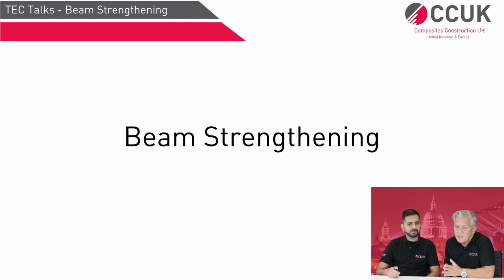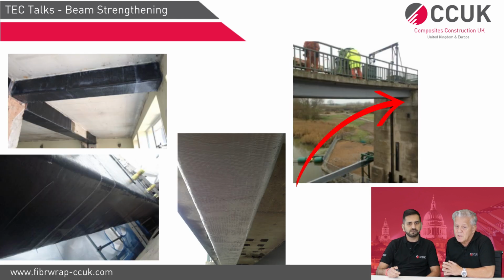So if we're looking now specifically at the beam strengthening side, when you're looking at beam strengthening, what are the key areas? Yeah, so beam strengthening is one of the most common types of strengthening which is done using carbon fibre. Generally beam strengthening is done as it's a flexural element. So mainly the reason for strengthening a beam is probably the flexural requirement, so you can strengthen it for increased sagging moments or increased hogging moments, and also beams are strengthened for shear.